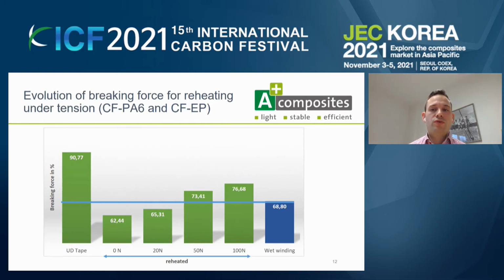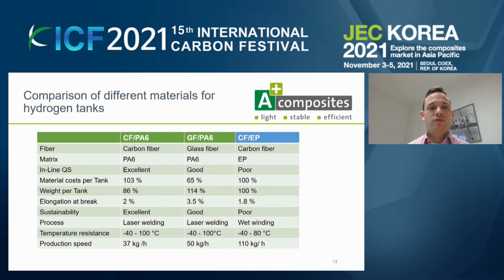If you compare this now with the wet winding process, where we have applied a 50 Newton pre-tension, you see that the magnitude is the same when you reheat it without applying the thermoplastic impregnation and the spreadability. So you lose about 30% of your performance, which is quite a lot. And this gives us a good idea how thermoplastics can improve and decrease weight for pressure vessels, for example. And this you can see in this slide of the comparison of different materials for hydrogen tanks. So this is a theoretical